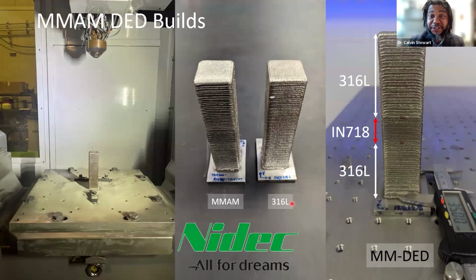Now from this, we've got a lot more steps to make. We've got to go from just doing notch strengthening to saying, well, hey, what about high temperature? We're trying to get to extremes, right? What happens when we take this to 1,000 degrees Celsius or 1,400 degrees Celsius? What happens when we subject it to dynamic loading conditions and crack initiation, fatigue crack growth may be a concern? What happens if we take it to super high hertz and we start to have things like wear resistance occur?